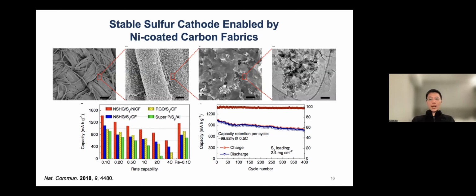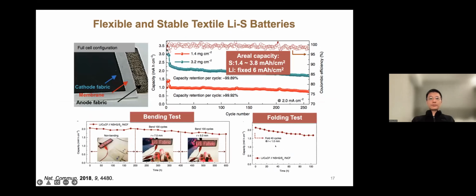So at that time, we demonstrate if you assemble these two pieces together, and then you can get a decent cell with a very little amount of lithium metal on the anode. We fix it at 6 milliampere hour per centimeter. Sulfur loading varies, so the DOD is actually quite deep if you think about this paper was published in 2018. And then therefore the energy density in terms of the stability at this energy density and the flexibility, it was pretty good and surprisingly good, I would say, to us.